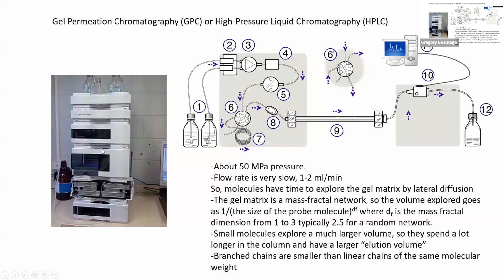So you have to figure out how you would distinguish between a high molecular weight branched polymer and a low molecular weight linear polymer. And you do that by having different detectors on it. That's why this thing has a stack here. If you use light scattering, you get the weight average molecular weight, but it's an absolute weight average molecular weight. So that's just a straight number, and that doesn't have to do with branching or not branching. In other words, the retention time has to do with the volume of the molecule. But if you shoot a beam of light through it and get the light scattering pattern, that's a tag of a fixed actual molecular weight. So by your standards, you would say it's 1,000 molecular weight, but by your light scattering, it's coming out like 100,000. Then you know that's a branched molecule.